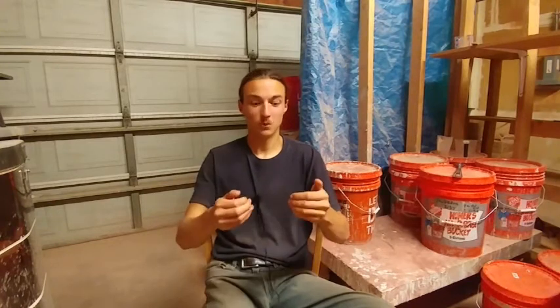And that can help quite a bit with that problem. Now, the other problem would be pinholing and blistering, and this really is due in part to gassing out. After certain materials gas out, the glaze is not able to recover as it cools down. It doesn't have the chance to cover up the hole, so when you have the finished piece, you have pinholing, which is basically little holes in your glaze. That's due to gassing out, and blistering is just a more severe case of it. Basically the same thing, but worse.